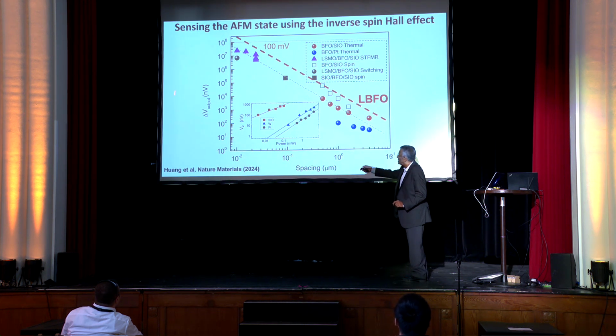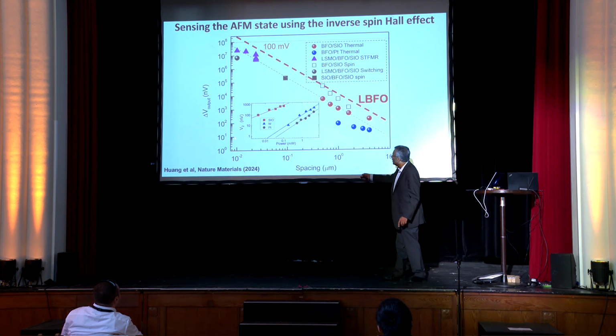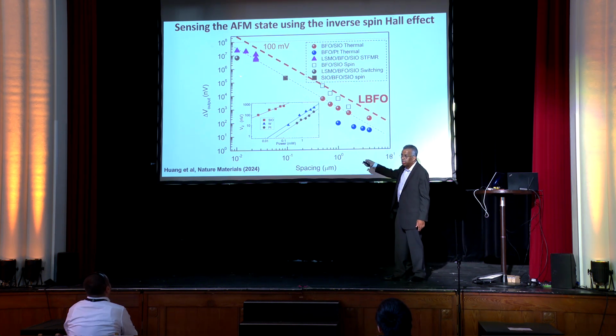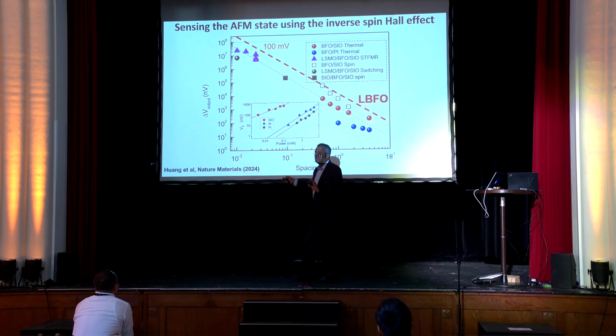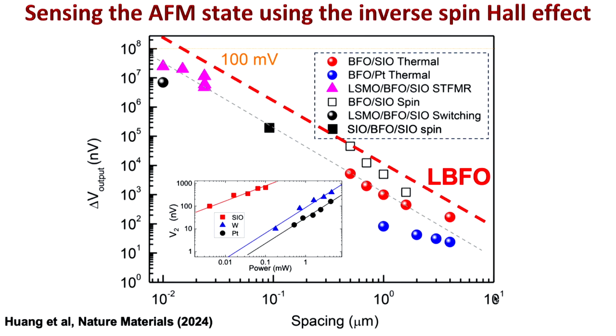What you plot here is the output voltage as a function of the spacing. And going down to about 10 nanometers, which is kind of like a vertical structure, we think we can get to 10 millivolts output. This is the spin Hall voltage. But it's measured in a very careful way. You cannot do DC because of leakage issues. So you have to do a resonance-based measurement. But the message I wanted to give you is, by making these perfect materials, indeed, it may be possible to